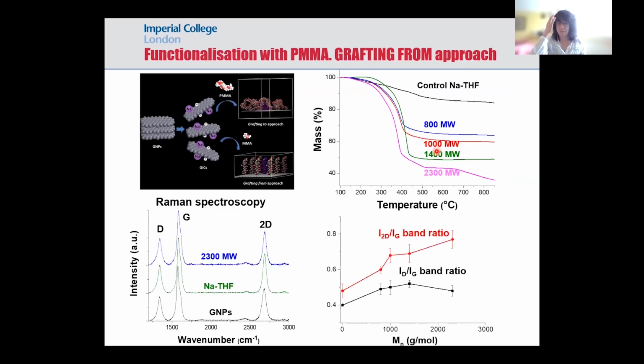Raman spectroscopy also confirmed that we were functionalizing the graphene with this polymer. We focus on the D band, which is indicative of defects. From these D to G ratios, we observe in this graph that as we increase the molecular weight of the polymer, we observe an increase in the D to G ratio, meaning that we are introducing defects on the graphene layer from these polymers on the structure.